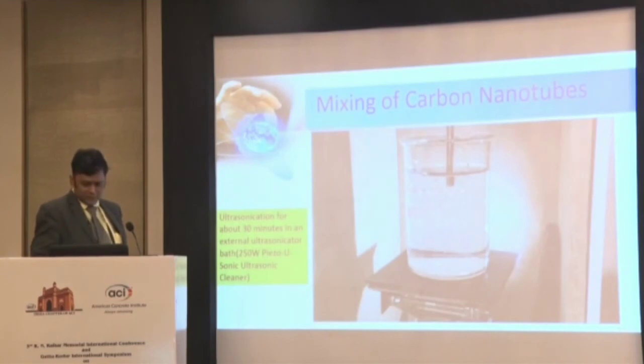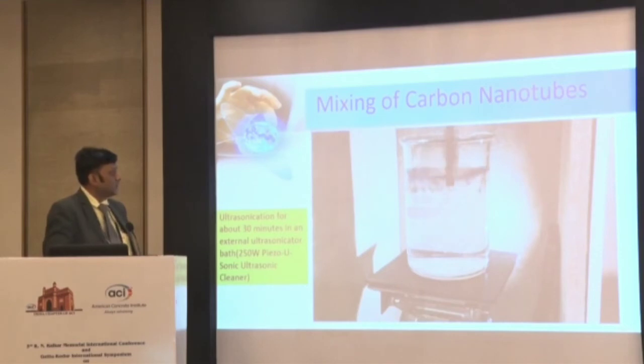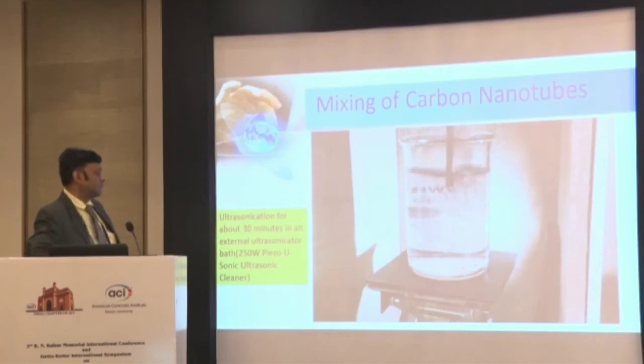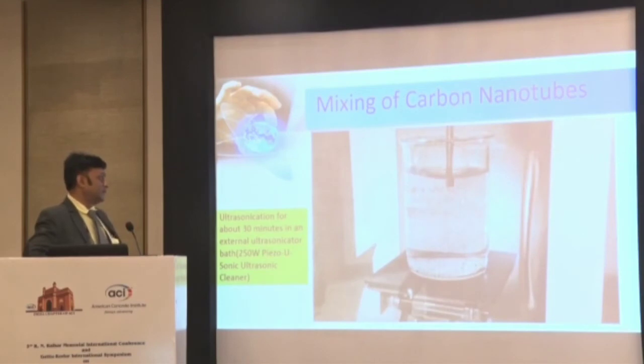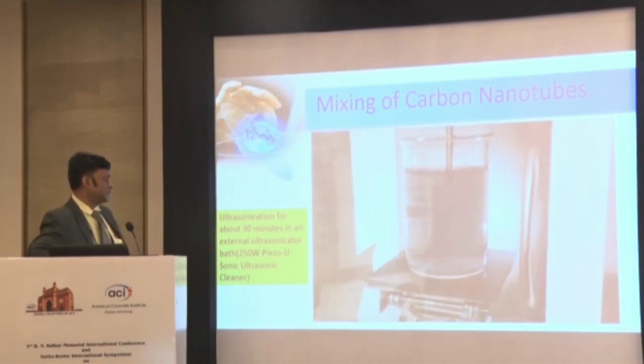Now this is a video showing how CNT does not dissolve in water. People get a problem here. They think adding CNT in cement will give you strength, or adding titanium dioxide in cement, or adding nanosilica in powder form, but this is a great problem. So we have used ultrasonication for 30 minutes in an external ultrasonicator of our IIST lab, a 250 watt piezo U-sonic ultrasonic cleaner. This helps in breaking the bonds by ultrasonic energy, external, not internal.